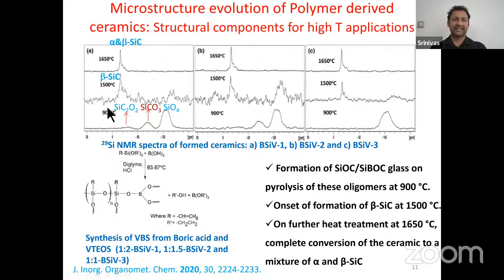This polymer is given different heat treatments: 900 degrees centigrade, 1500 degrees centigrade, and 1650 degrees centigrade, as you see in the three spectra on the left side. To withstand high temperatures, more than 2000 degrees centigrade, we need a silicon carbide system. At 900 degrees centigrade, SiC formation is not there in any of the three cases. At 1500 degrees, initial beta silicon carbide formation is there in all three systems, but a SiO4 phase is still present. At 1650 degrees centigrade, both alpha and beta silicon carbide have evolved in all three systems.